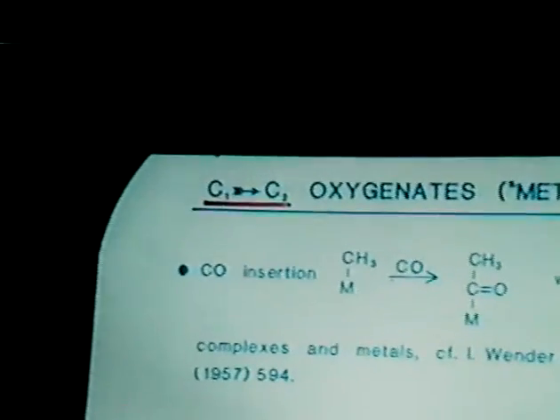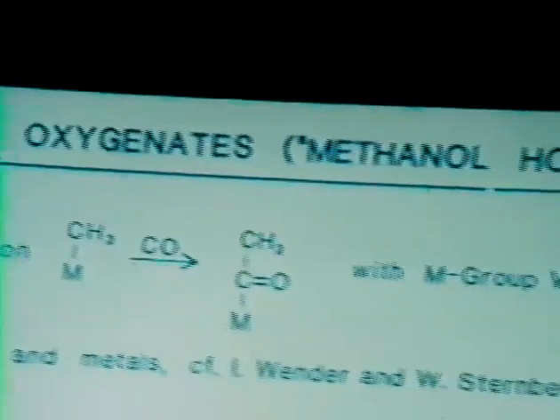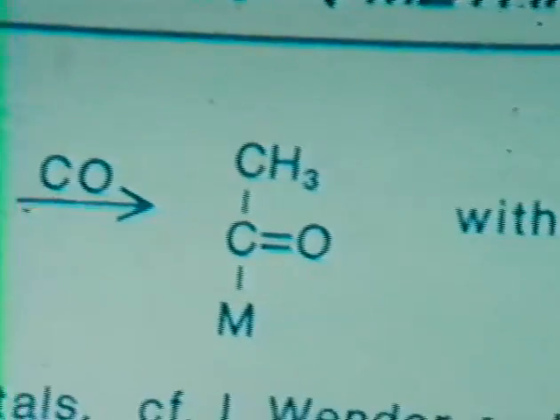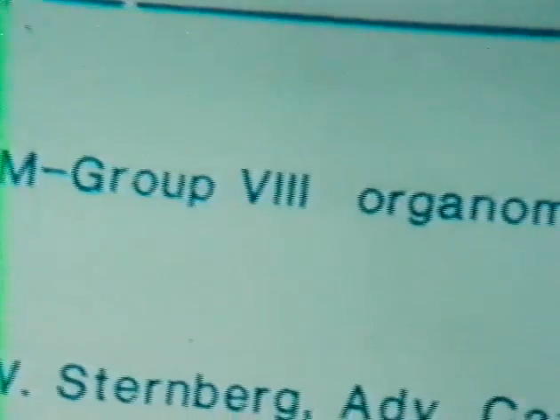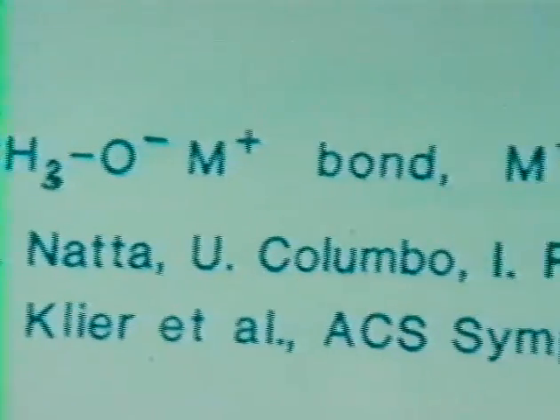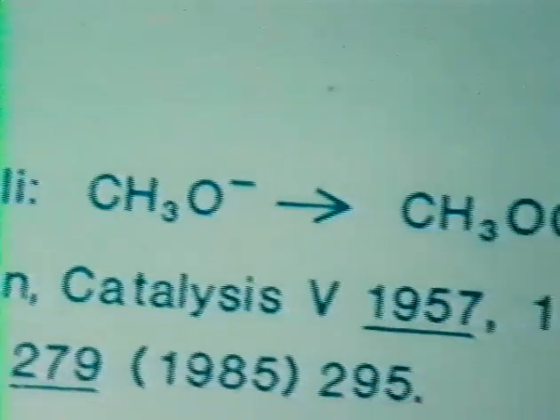If one changes conditions, one can get on in this system to higher alcohols. The conditions are higher temperatures and lower hydrogen to CO ratio. And the first step in that higher alcohol synthesis must be C1 to C2 step. Several mechanisms have been proposed in the past. Classical organometallic synthetic insertion of carbon monoxide into alkyl metal bond. CO insertion, and we thought initially that this could be working. Insertion into the methoxide bond to make an acetate ion, which is then hydrogenated to ethanol.